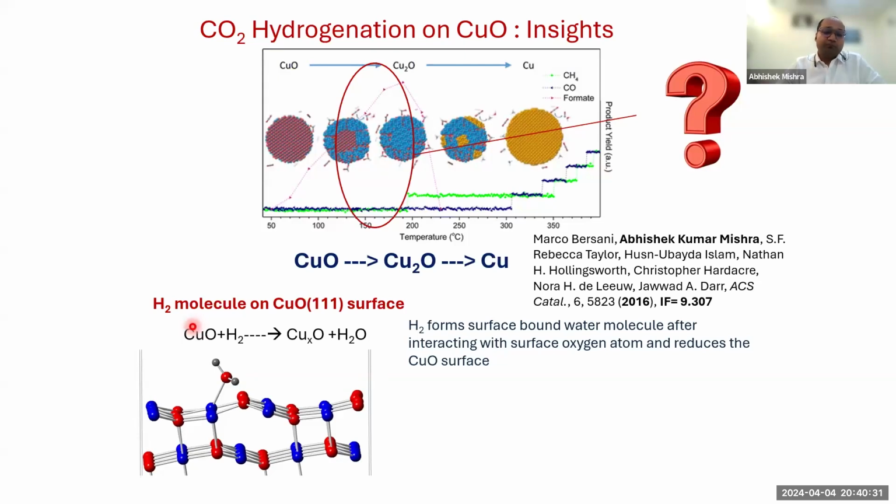So CuO is getting converted at some point to Cu2O, which was happening here. More and more oxygen will bond with the hydrogen molecule to form a surface bound water molecule over the surface, and that's what our experimental partners found in their experimentations. So the one puzzle was solved here, why this was reducing to, finally, the copper electrode.